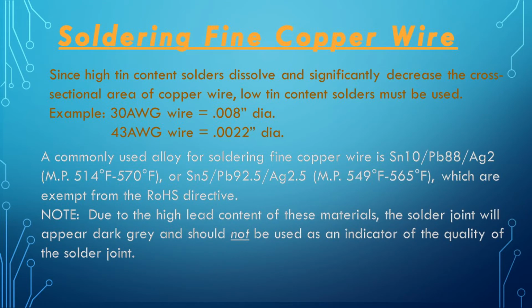For those of you that may be soldering fine copper wire, like for coils, transformers, guitar pickups, and other applications, we need to use a solder alloy designed for that application. Since we know that tin readily dissolves copper, when we attempt to solder fine copper wire, we will greatly reduce the cross-sectional area of the wire and severely weaken the wire at the point where it exits the solder joint. Therefore, we need to use a low tin, high lead alloy like 10/88/2, tin lead silver. It has a higher melting temperature, but it will not dissolve a significant amount of copper. This alloy that I mentioned and the one I have listed on this slide are exempt from the RoHS directive that I just talked about, since this is really the only way to solder a fine copper wire.